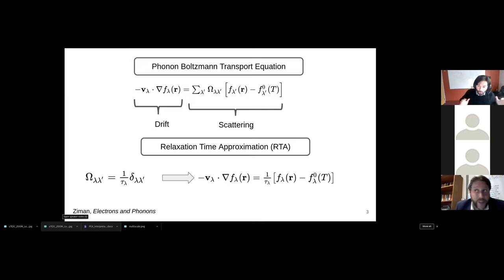So we need to move beyond standard diffusive theory, and the model of choice in this case is the phonon Boltzmann transport equation. Here you can see the steady state form of the BTE. On the left side we have the drift component, and on the right side the scattering component. f_lambda is a non-equilibrium phonon distribution for phonon mode lambda, which collectively describes the phonon wave vector and polarization. Here f zero is the equilibrium distribution at a given temperature, and omega lambda lambda prime is the scattering operator. Those contributions are computed by first principle calculations, for example density functional theory.